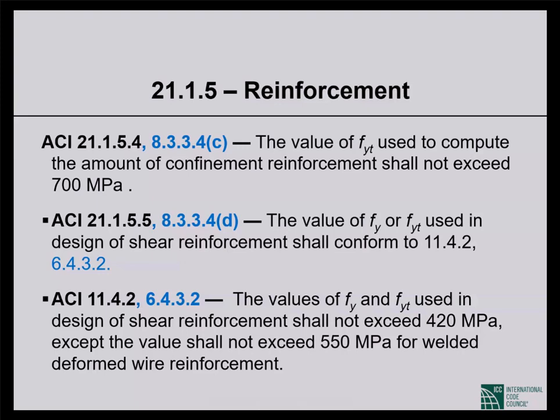If we allow shear computations based on higher yield strength, then we'll be looking at wide shear cracks, which are very objectionable. So this is why the restriction. But for confinement purposes, we are allowed up to 100 ksi yield strength of the transverse reinforcement. And yesterday I explained why that is very significant indeed.